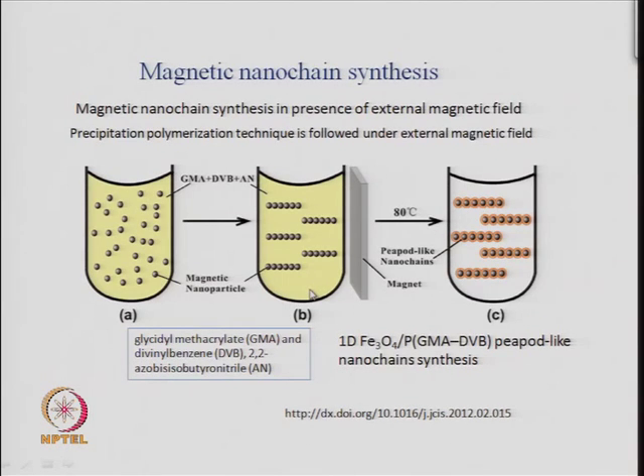Now, this is one methodology, there are many other methodologies by which nano chains can be created, and here the method is what is called precipitation polymerization technique, and it uses this kind of polymerizing agents and monomers to form polymers at a particular temperature. So, these are iron oxide, it is one dimensional, so it is 1D Fe3O4, because it is chains. So, 1D Fe3O4 chains with a pea pod like polymer covering it on top. So, this is a very interesting method of making a self assembled chain of magnetic nanoparticles, specifically of iron oxide, and can be used for several applications.